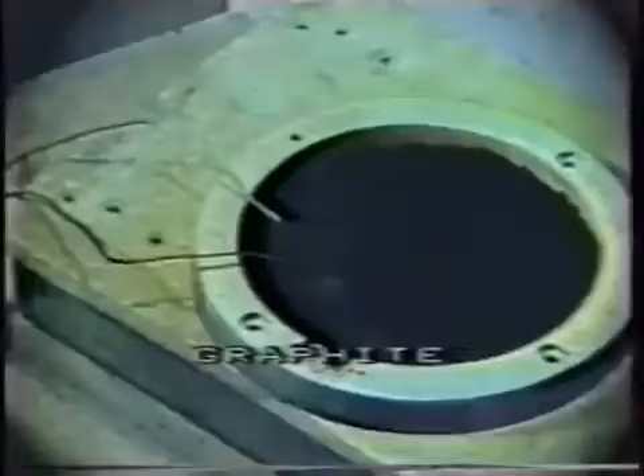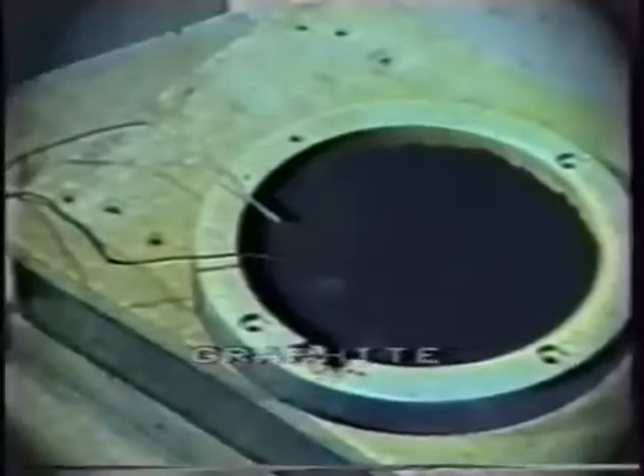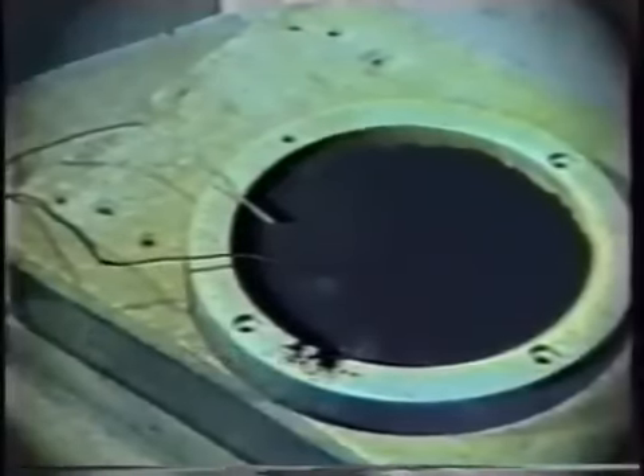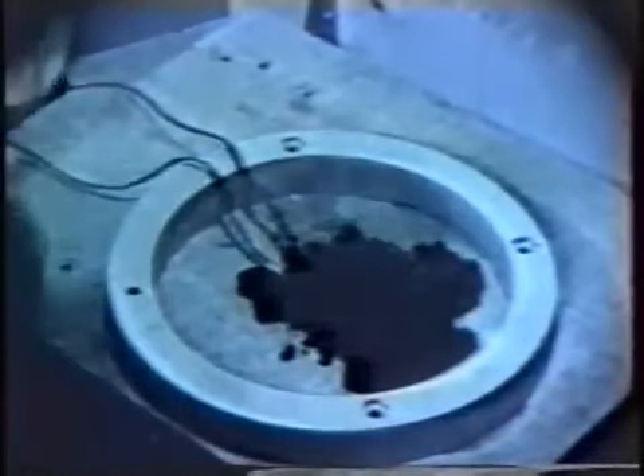And all over our test here, and the test was terminated by using some magnesium oxide sand on it. But the graphite just was not effective. It did not remove enough heat and wasn't effective in extinguishing the fire.